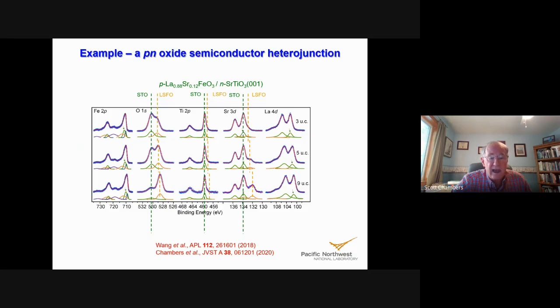And notice that for the materials that are in the film, the binding energy is changing. The binding energy shift relative to the substrate is going up with thickness, because this is 3, 6, and 9 unit cells. In the case of the iron 2p, it's really complicated, because for every strontium that goes into the material and replaces a lanthanum, one of the irons goes from formally 3+ to formally 4+. So you have a mix of iron 3 and iron 4, making for a horribly complicated spectrum. We're not going to even play with that.